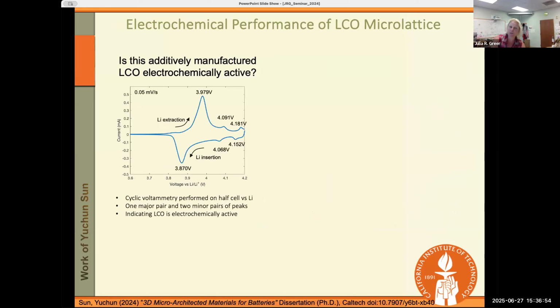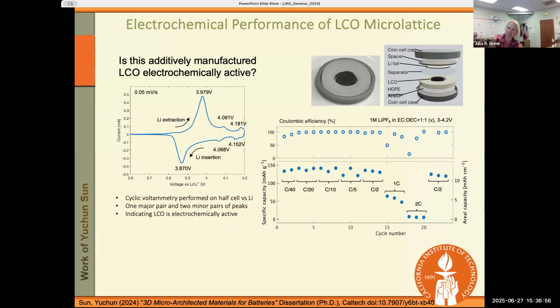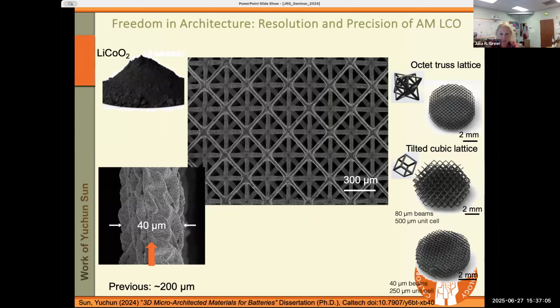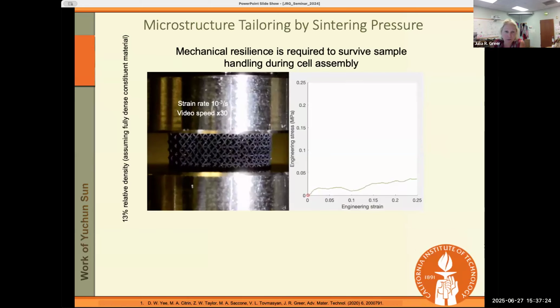So Yuchun was able to characterize this as a battery performance, and sure enough, this paves the way for maybe more efficient solid state batteries sometime, and they're quite robust. What Yuchun was able to also demonstrate is that she can get to dimensions that are much smaller than the ones that have been reported before. She can push them down to about 40 microns and even below, whereas all previous reports show hundreds of microns thicknesses. So this is making it possible for us to make much smaller battery electrodes.